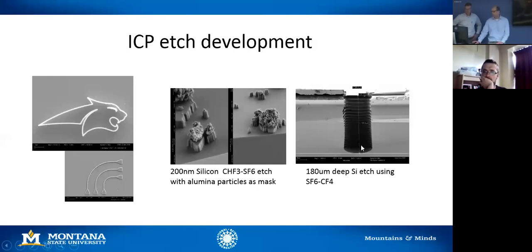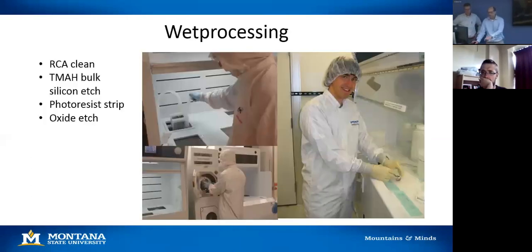If you want to go all the way through, wafers are 0.5 millimeter thick, we can use a pseudo-Bosch process, they call it, where you cycle between etching the silicon and passivating the sidewalls of the silicon. So you can just work your way through, and that's the scalloping features you see. So it allows us to do very deep etches. Depending upon the needs, we have a lot of different tools or processes we can use.